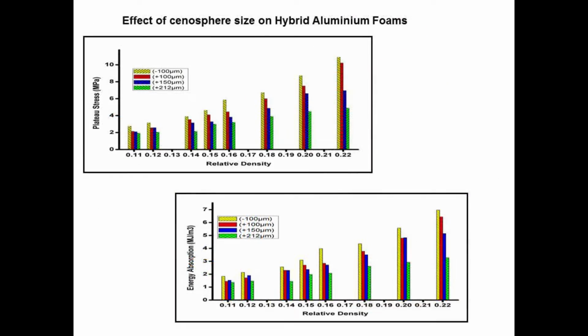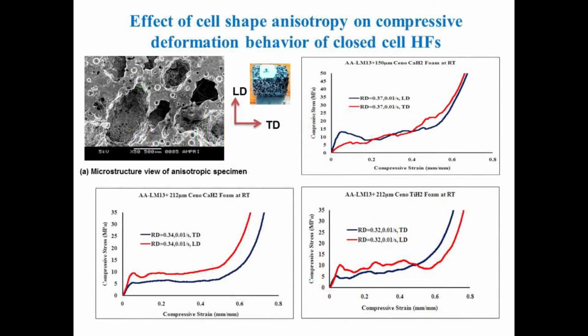And these are the different ways we have optimized the process parameters as well as the cenosphere size. This material has a lot of future because through the use of cenosphere, which is a thermal power plant ash, the foam cost could be reduced significantly by 30 to 40%, where the cells of the cenosphere will give additional strength within the foam. So we will get the strength as well as more energy absorption, and we can reduce the cost of the foam through the use of these micro balloons, which are called cenospheres, within the metal.